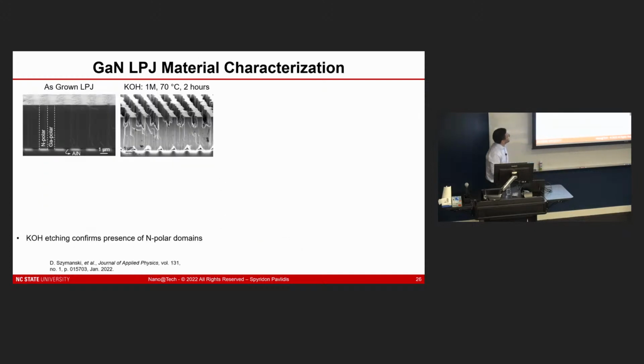We then went ahead and analyzed this in a few different ways. The first is we did what people normally do when they want to make sure they have nitrogen polar GaN, which is we dip this in hot KOH, and indeed we can see selective etching. So we can see that we are removing these pillars where the nitrogen polar GaN was grown. So you can see a periodic arrangement of these nitrogen polar and gallium polar domains side by side.